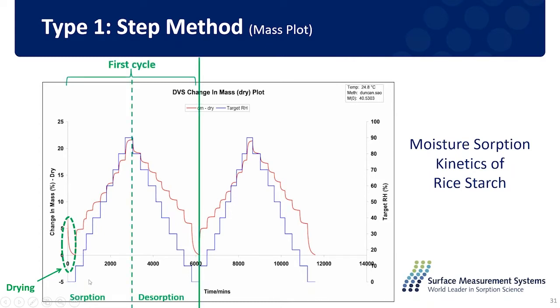Then we can know the initial moisture content inside the material for the starch sample. And we set up the first cycle for the sorption and desorption, and the second cycle on the same material. So what we notice here is the second cycle is exactly identical to the first cycle. So basically it's a fully reversible process for this moisture sorption of the starch sample.